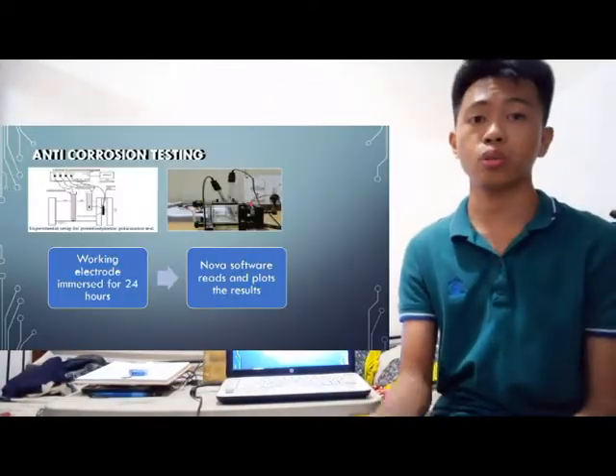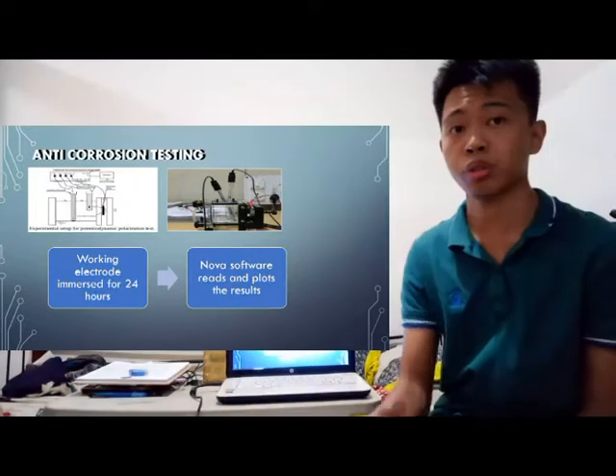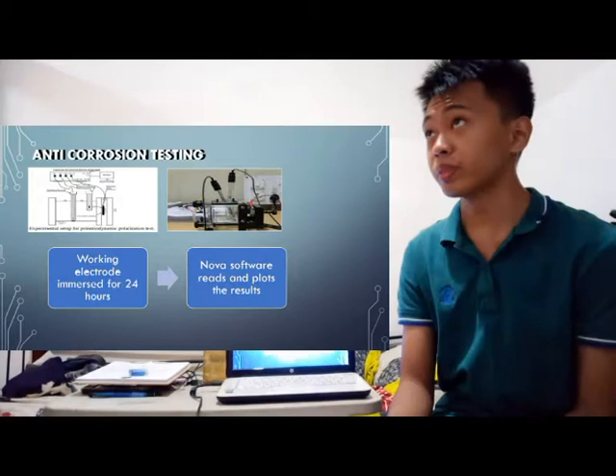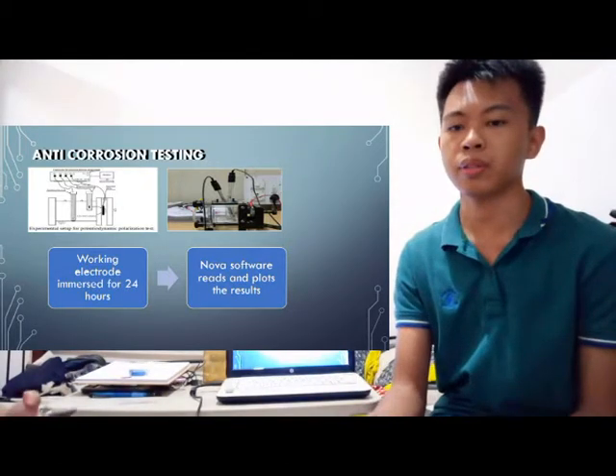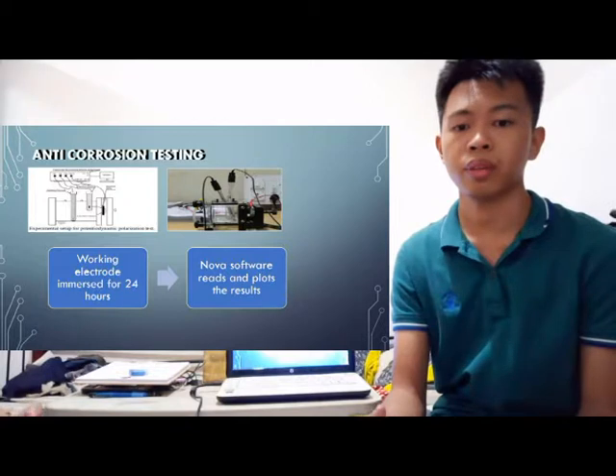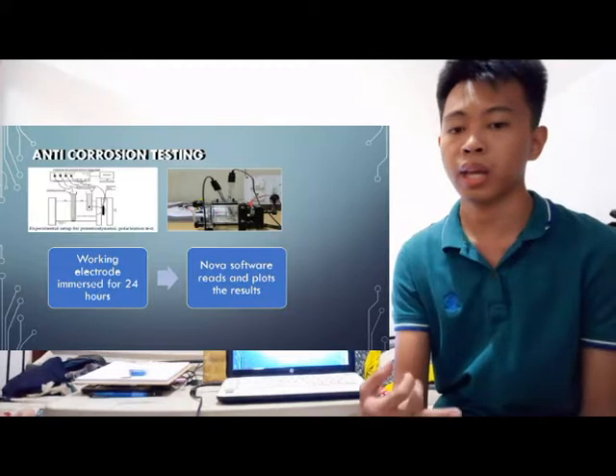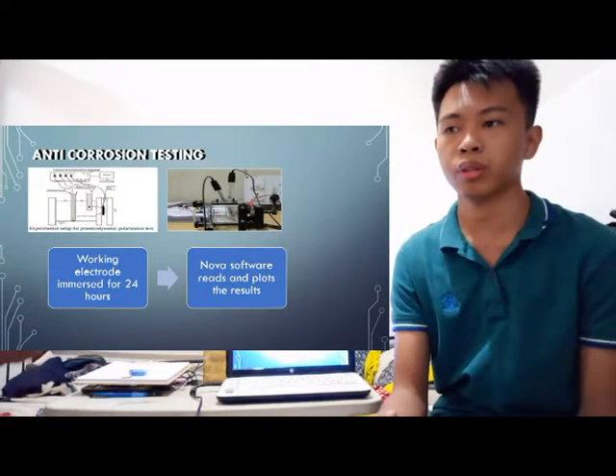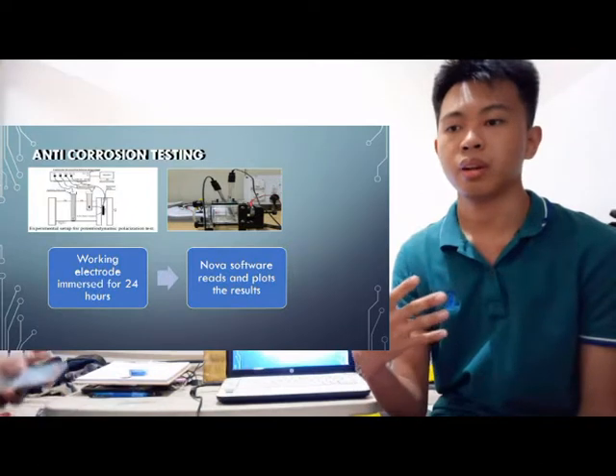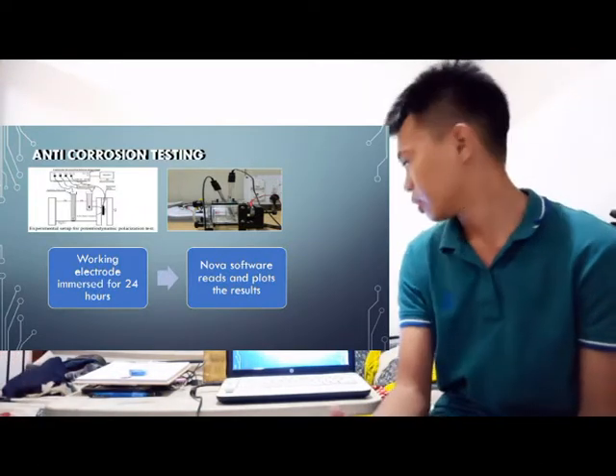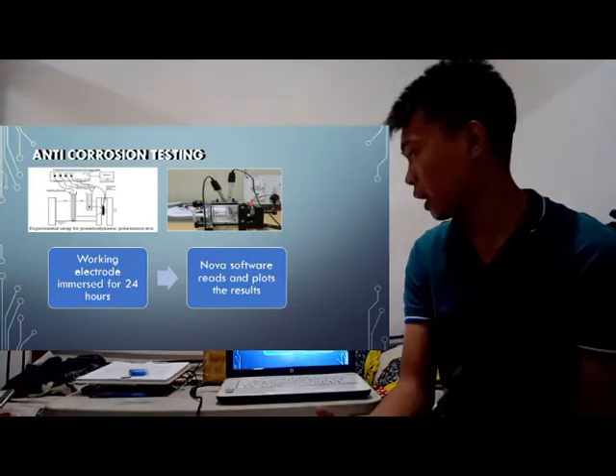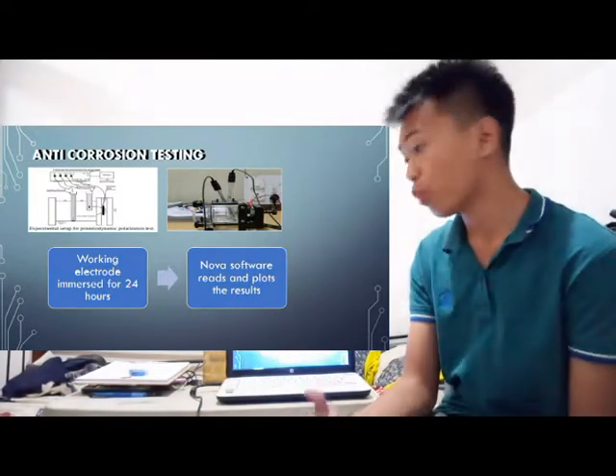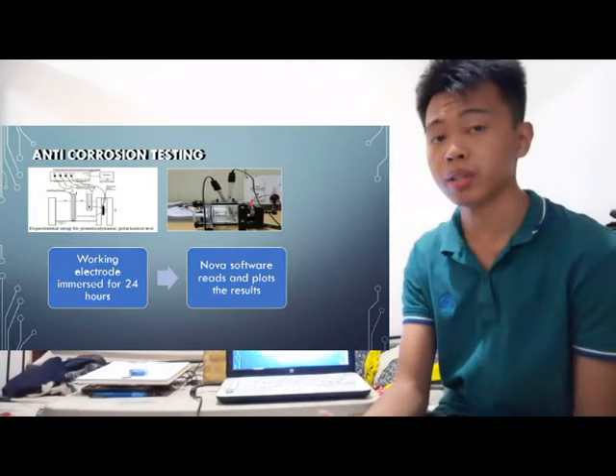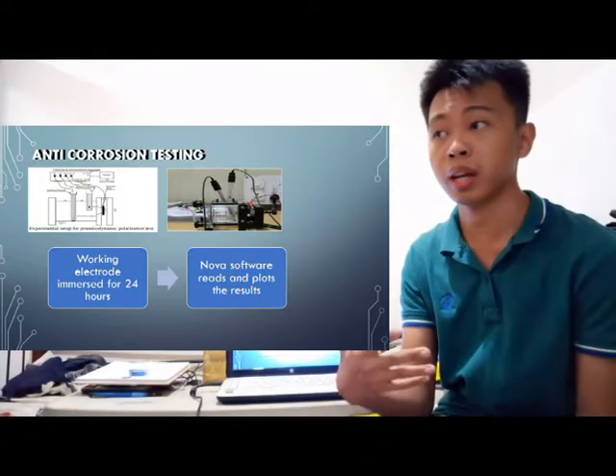To evaluate the performance of our coating, we subject it to anti-corrosion testing. Generally, we fabricated 3 samples. The first sample is the stainless steel alone. The second sample is coated with polyaniline. The third sample is coated with our material, the PZN or polyaniline zeolite solution. For the anti-corrosion testing, our working electrode is immersed for 24 hours. The working electrode should be the coated panel.